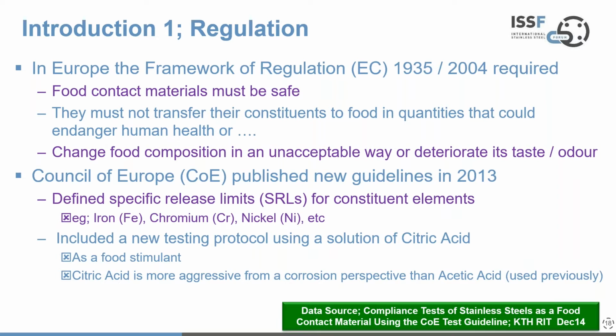So this starts to bring together those 3 features that I talked about in the opening of this presentation. And the Council of Europe produced new guidelines in 2013, so not that long ago. And within that, there were defined specific release limits for the constituent elements of materials, which in the case of stainless steels, we'd look primarily at iron, chromium, and nickel. There are other materials, but I'm going to use these as illustrative of what levels are released. But also in this new guideline was a new testing protocol using a solution of citric acid as a food simulant, and that replaced, from a corrosion perspective, acetic acid that had been used previously, and citric acid is more aggressive. So this was seen as a tougher test.